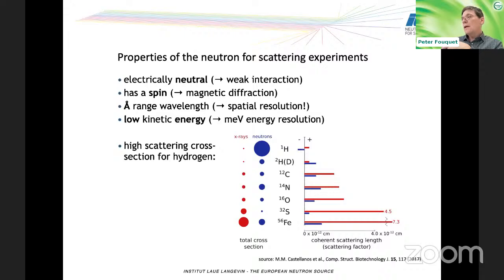And what's very interesting, that makes the neutrons very complementary to X-rays. That's shown here on the right-hand side graph. When you look at the scattering cross sections of X-rays on the left and neutrons on the right, you see that for X-rays, the scattering cross section is guided by the number of electrons in the material, in the atoms. Whereas for neutrons, we have a nuclear interaction, and by quantum mechanical effects, the neutrons have the highest scattering cross-section for hydrogen, which makes hydrogen very, very visible for us.